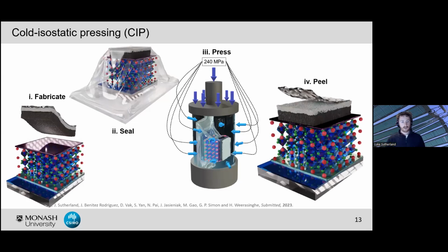And just for a little bit of context here, for the 240 megapascals, which was our optimized pressure in the end, the time it takes to pressurize our chamber, hold at 240 megapascals for 30 seconds and then depressurize, is 3 minutes in total. So only 3 minutes. And the chamber that we're using is a research scale chamber, 10 centimeter diameter and about 50 centimeter depth. And we can stack that, we usually did tens of devices at a time, but you could easily go to hundreds or even more.